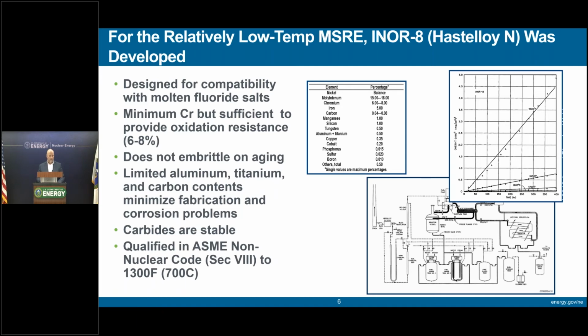So the first bullet here, we need these to be designed for compatibility with molten fluoride salts. They need to have a minimum chromium, but sufficient to provide oxidation resistance. They do not embrittle on aging. They have limited aluminum, titanium, and carbon contents, minimizing fabrication and corrosive problems. Carbides are stable and qualified in the ASME non-nuclear code Section VIII to 700 degrees C.